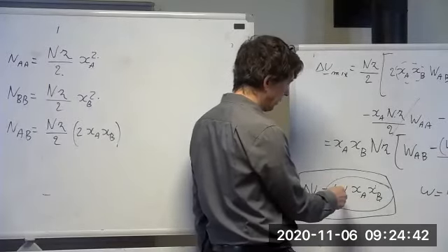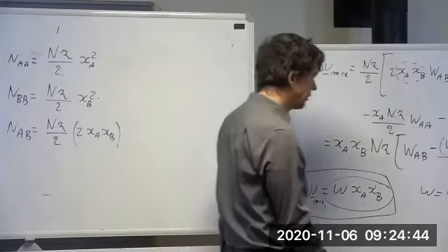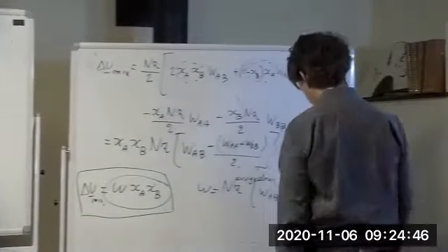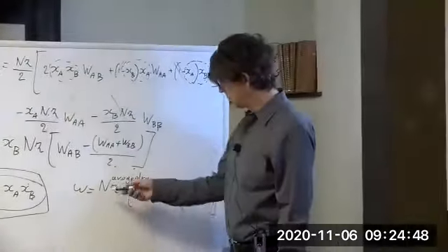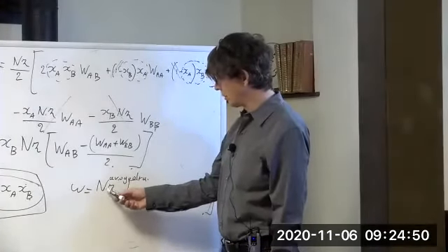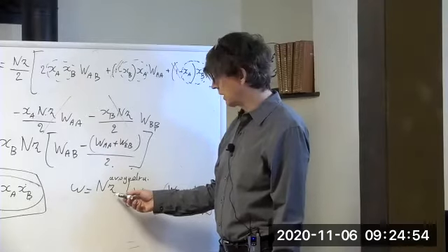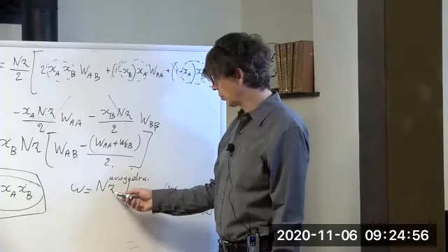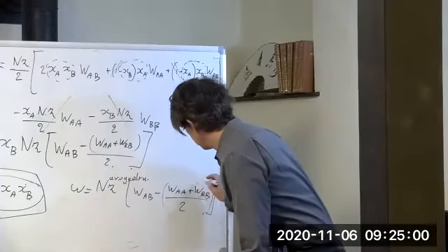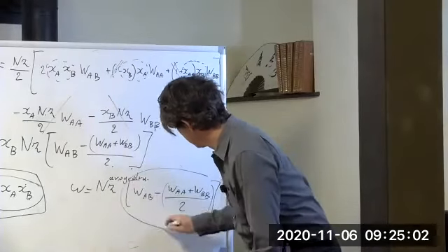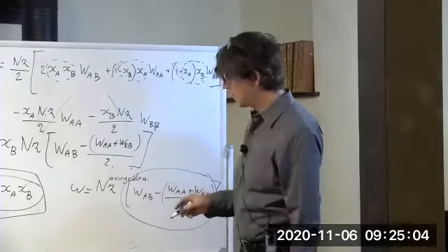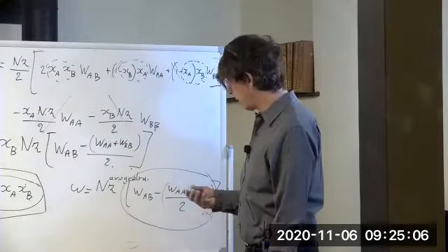And the prefactor, the energetic quantity, what does it contain? Well, it contains some reference stuff, right? The fact that we're doing it per mole, so N is N Avogadro. Z is just a small integer, the coordination number. But the important thing is this here. Omega is proportional to the bond energetics.